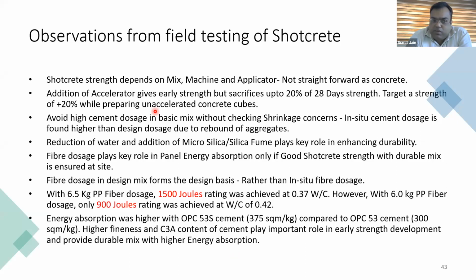Then one should avoid a very high cement dosage in the basic mix because it incurs shrinkage and thermal cracks in the tunnel lining. And one should be aware that the in situ cement dosage is always higher than what you have designed. Supposing you are using a dosage of 400 kgs of cement, the in situ dosage will be more than that, because when you are applying the Shotcrete, most of the aggregates get rebounded, but the cement stays in its place. So the dosage in situ is very high.